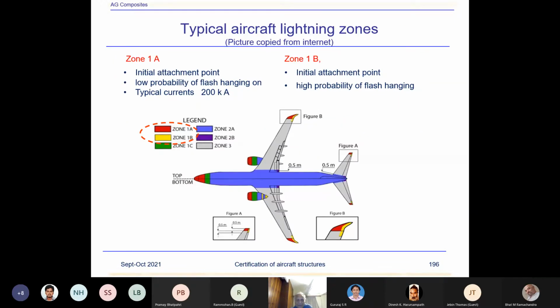Okay, now just to explain some zones. This is an aircraft picture I've just picked up from the internet as a typical picture. We define the lightning strike in three zones of the aircraft. Zone 1A and 1B are shown by this red. Essentially, the highest current occurs in this 1A zone. Initial attachment point, low probability of flash hanging on, and typical current is 200,000 ampere, which is pretty high, causing damage which normally occurs on the leading edges, as you can see on the surface. 1B, initial attachment point and high probability of flash hanging on. This is the difference between these two, and current levels are high.